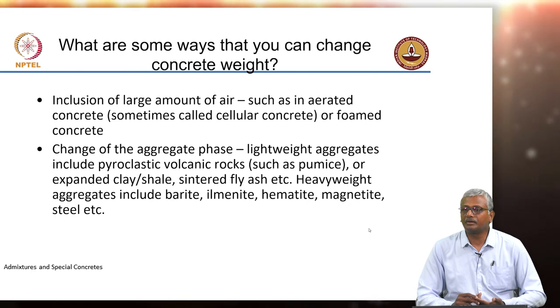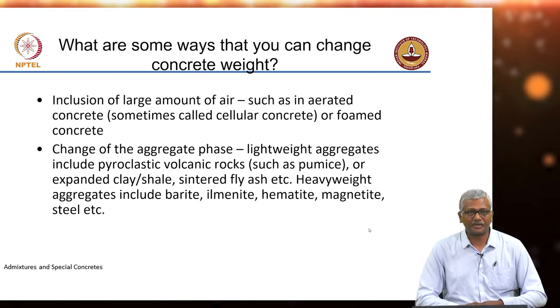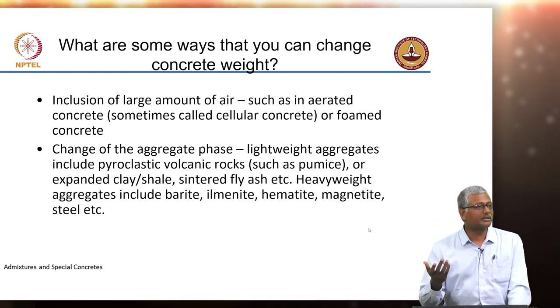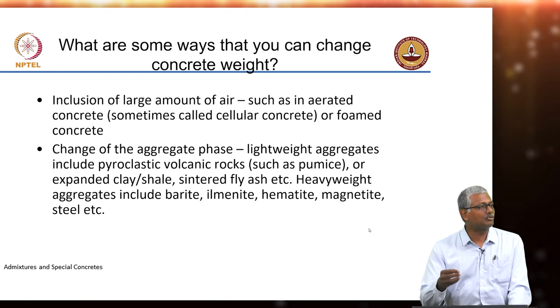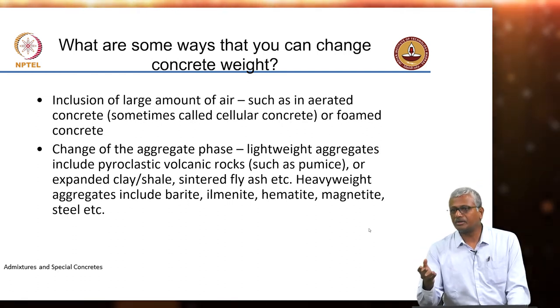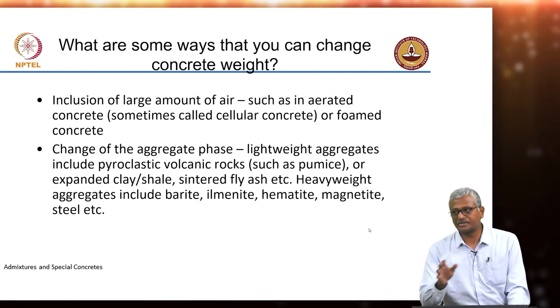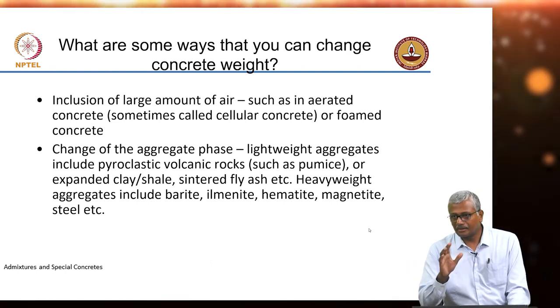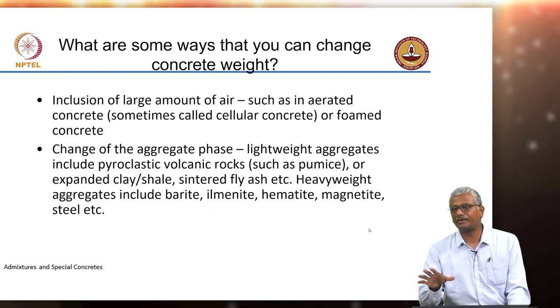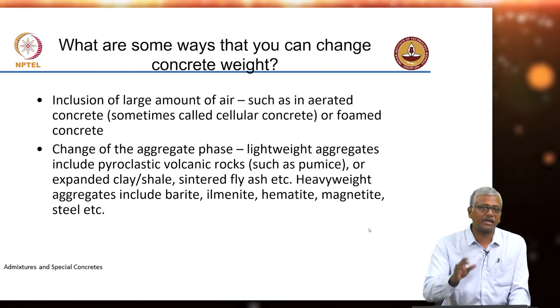Alternatively, if you want to make concrete lightweight you can also introduce more air into the system. We already know about air entrained concrete, but air entrained concrete has an air content of only about 5 to 8 percent. At that air content, your density is not going to reduce to much lower than 2200, so it does not qualify as lightweight concrete — it is still normal air entrained concrete.